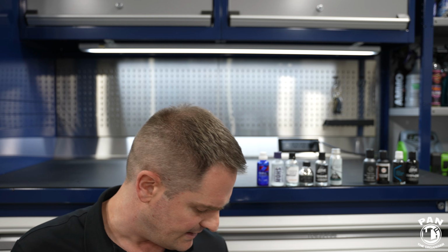First of all, before you apply coating, there are a few precautions that I want to share with you. Of course, always work in a well-ventilated space. That is the first key thing. If you guys have a garage like I do, fantastic. You can work in controlled conditions. The best ambient temperature to be working in for coatings is anywhere around 20 degrees Celsius or 68 degrees Fahrenheit and roughly 40 to 45% humidity. So those are optimal conditions, right?